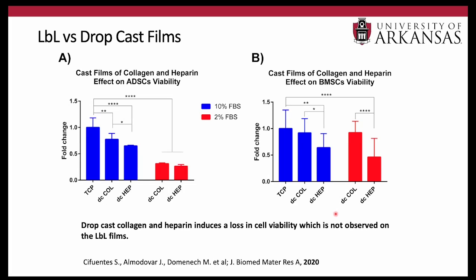Lastly, we wanted to compare: is it really something about the layer-by-layer films, or is it just one component versus the other? So we did a study where we made cast films of just collagen or just heparin, and we studied cell viability, using both adipose-derived MSCs and bone marrow-derived MSCs. What we saw, which was quite interesting, is that when we used the surfaces alone, either collagen or heparin, not together in a layer-by-layer fashion, the viability actually decreases. So there's something about that layer-by-layer interaction that the cells like, as opposed to just one coating of collagen or one coating of heparin.